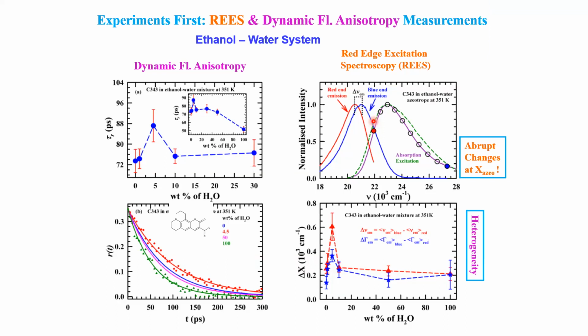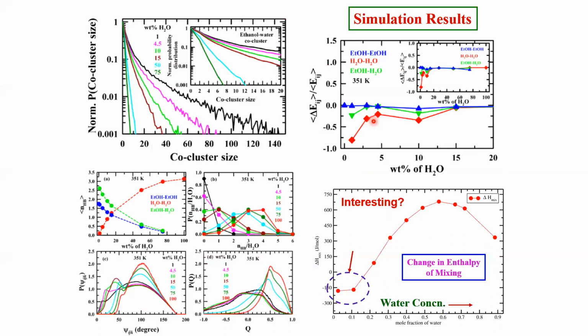Okay, because you are looking at low temperature, it's 351 Kelvin. It's not low, it's 351. That is very interesting, 351 Kelvin. So it's about 78. It's higher, high temperature. Yeah, that's why it's so interesting. There must be stable cluster formation, and that's what we are showing in simulations. Do you see that in anisotropy measurements?